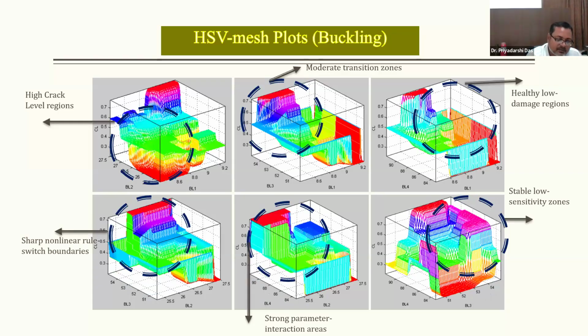So in this way, the HSV mesh plots can define the sharp color edges or boundaries that represent the rule switching behavior that demonstrates the fuzzy if-then rule: if the crack location zone corresponds to the geometrical configuration associated with the stiffness degradation. So from that fuzzy logic, we can clearly feel how the stiffness is degraded, and through that stiffness, how the structure is affected by the cracks. In this way, we can find the position of the crack and the depth of the crack. That means the crack severity towards its position and its depth can be realized.